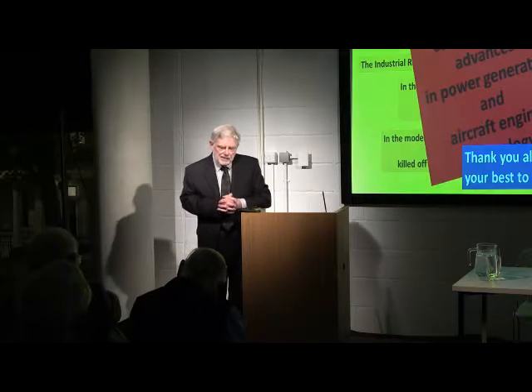Titanium has been the biggest disappointment to high-temperature metallurgists. It's got a melting point of something like 1660 degrees. And you would think, on that basis, it would be at least as good as iron or nickel. In actual fact, and it's obviously tied in with the structure of titanium, it's about as strong as mild steel. And mild steel starts to give out at around about 500 degrees. But there are two other problems with titanium, both of which are connected with oxidation.